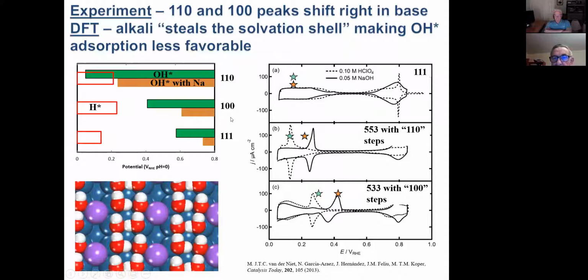And we can explain that in terms of the fact that these cations that are present when we move to a higher pH, we do that by adding sodium hydroxide into solution. And that sodium hydroxide will actually interact and destabilize the adsorbed hydroxide groups. And that might be counterintuitive: if I put a positively charged sodium there, it's going to actually make OH on the surface less stable.